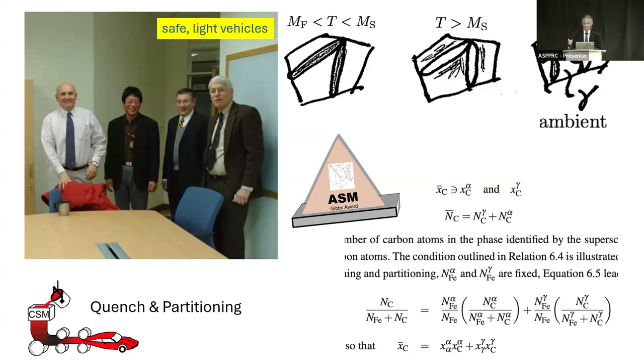This morning, Adira, and I think her second name was Balzac, explained the process. So I'm not going to go into it in detail, but in principle, it's very simple. You quench to partially transform into martensite, you heat it up so the carbon from the martensite escapes into the austenite and enriches it, and then you cool it so a little bit more martensite forms, and you've stabilized austenite. And that has beneficial properties.